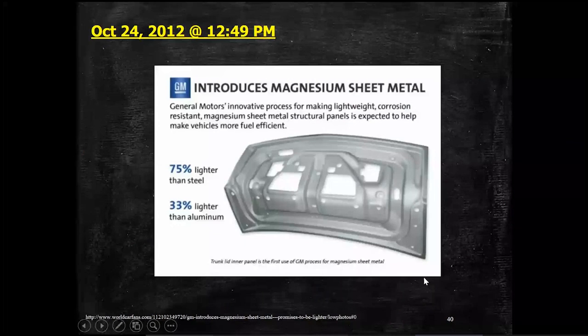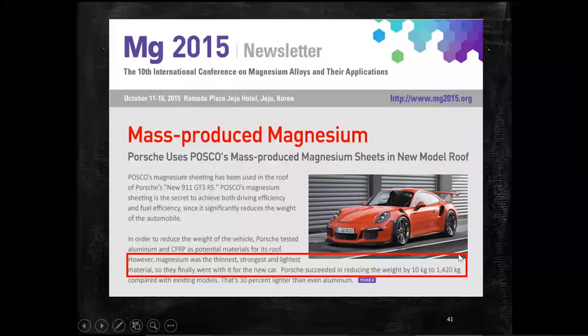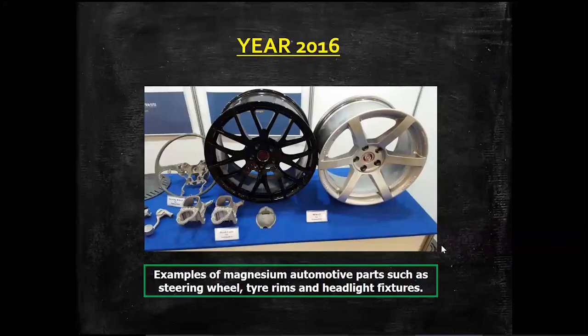Porsche in 2015 started using magnesium in the rooftop area, which is this area. And just by doing that, they saved 10 kg of the weight of the car. And they compared with aluminum and carbon fiber reinforced plastic, and they found that magnesium gives you the best option. South Korea has done a wonderful job to create a whole roadmap of using magnesium.